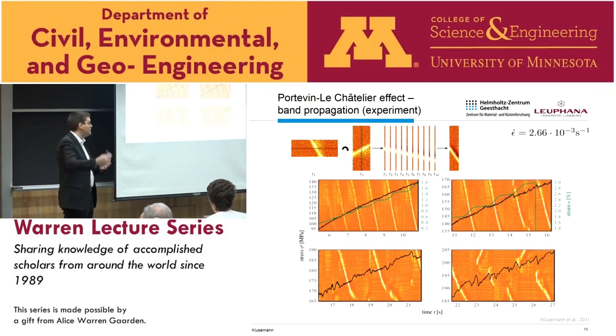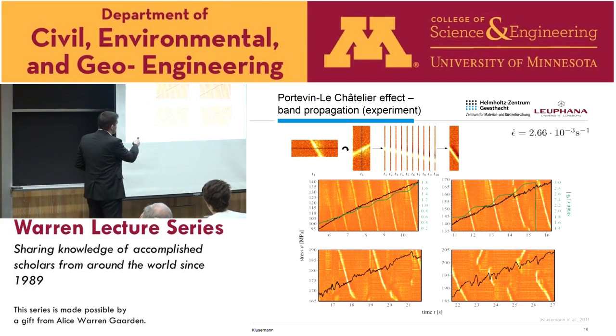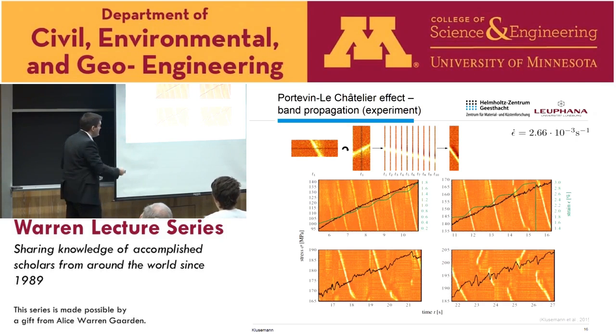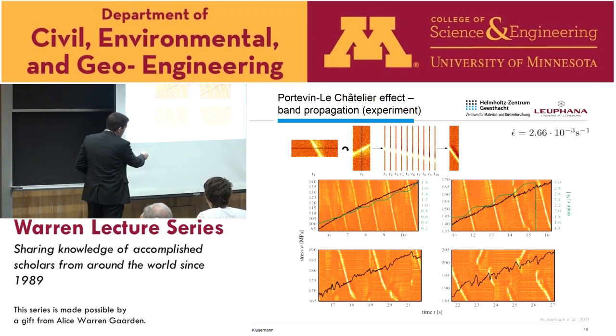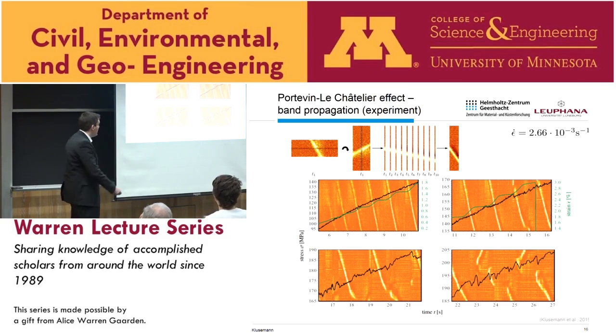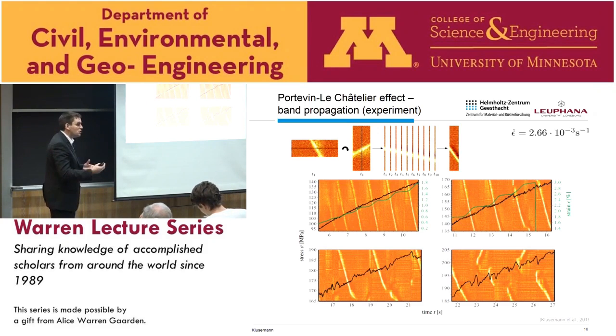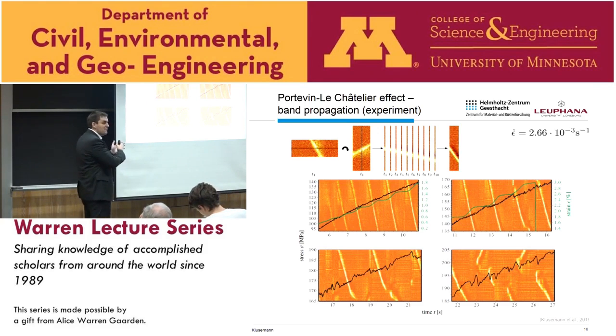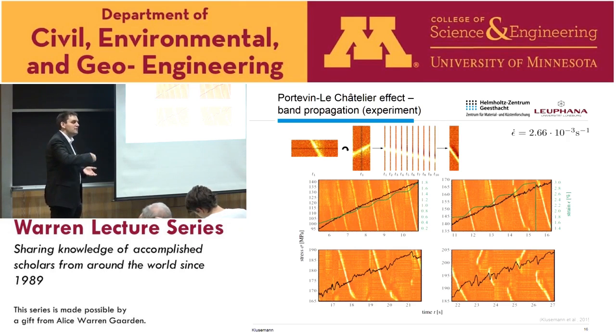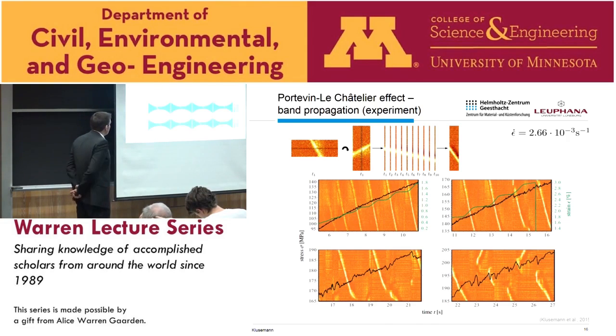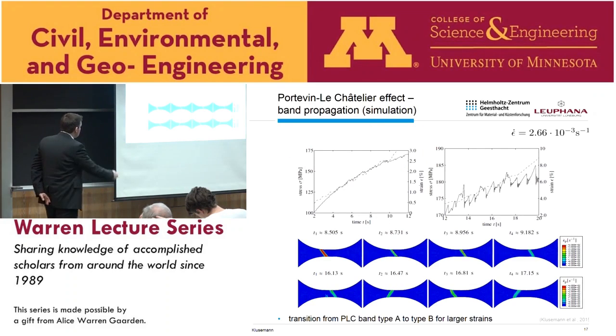As soon as we go to larger time steps, which of course also means the strain is increasing, we see changes in these PLC bands. First very continuous, and then later you see some broken points, and later on you completely see them starting, stopping, appearing again at the same position, propagating, and the same happens again. We also have much stronger oscillations, so classical type B behavior. So this shows that we have this transition from type A to type B, not only with decreasing strain rate, but also with increasing strain.